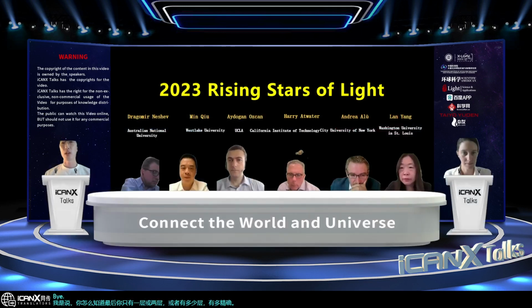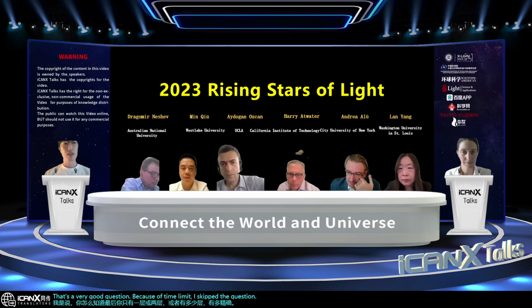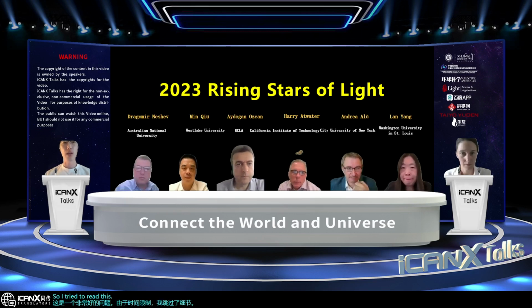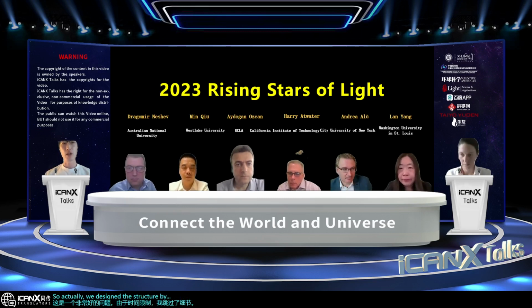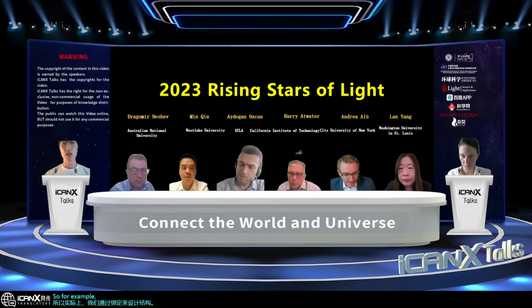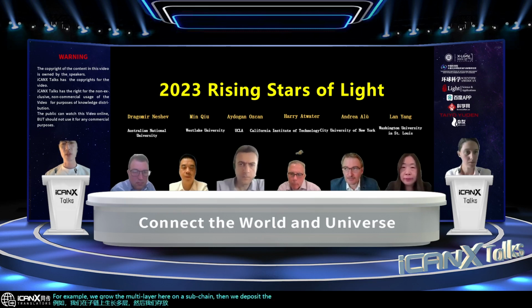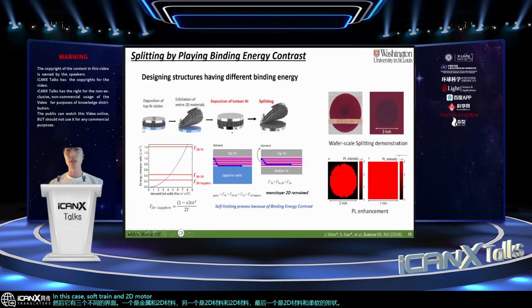Yeah, that's a very good question. Because of the time limit, I skipped the detail. Actually, we designed the structure by having binding energy contrast. For example, we grow the multilayer on a substrate, then we deposit metal on top. Then it has three different interfaces: one is the metal and 2D material, another is 2D material and 2D material, and the last one is 2D material and substrate. In this case, the interface between substrate and 2D material is the weakest. So when we apply energy here, separation happens at the very bottom side.